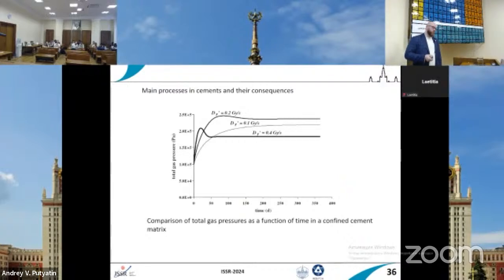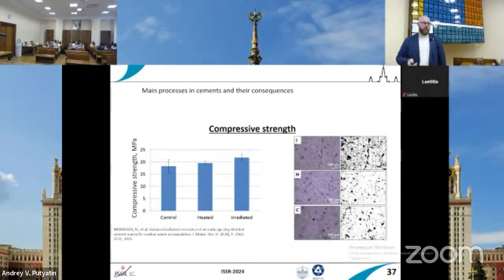The release of the gaseous products, or this gas pressure here, also depends not only on total dose, but also on the dose rate. Because if you have a very low dose rate, there is a possibility of recombination of the different species. So not only the total dose, but also the dose rate will affect the production of your gases, of your chemical species. Here again, you can see the increase in the mechanical strength of the irradiated cements, and again, the lower porosity of these materials.